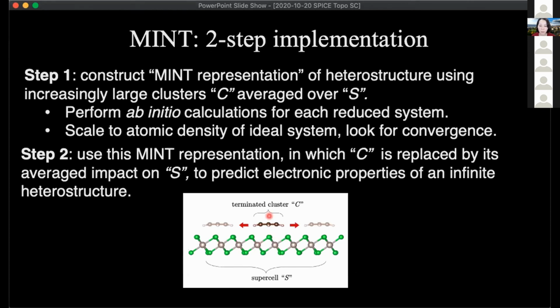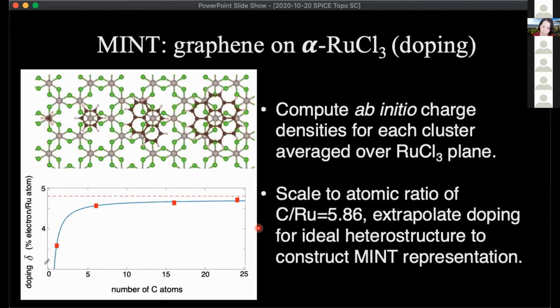So we study the system using DFT, and then we can study the electronic properties of that system. But we then systematically increase the flake size to see how quickly we can reach what would be the setting when both systems are macroscopic. The idea is when you have a mismatched system, if you go around the whole system, the registry would be averaging over all possibilities. So by studying reasonably sized flakes, our hope was that we should be able to mimic the macroscopic setting.